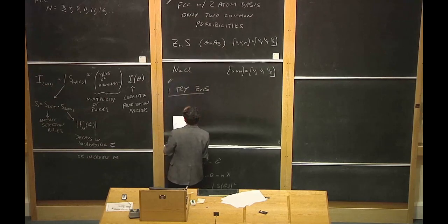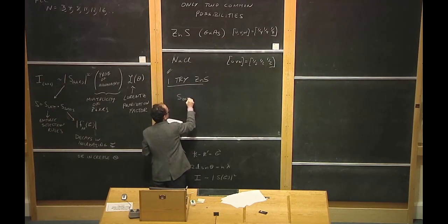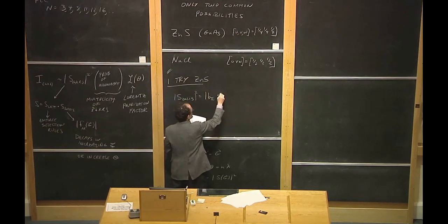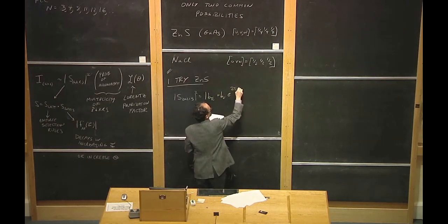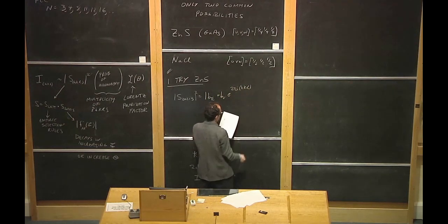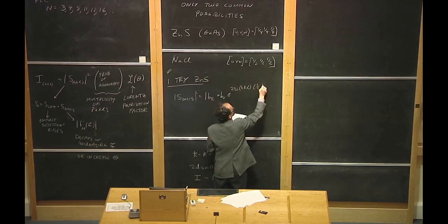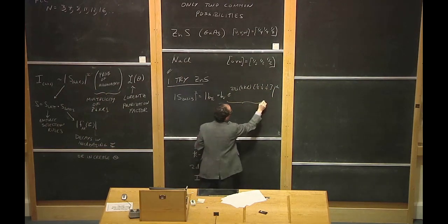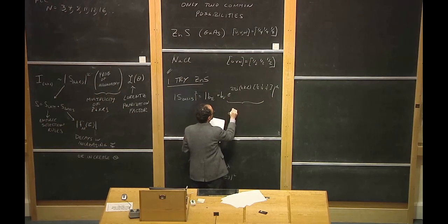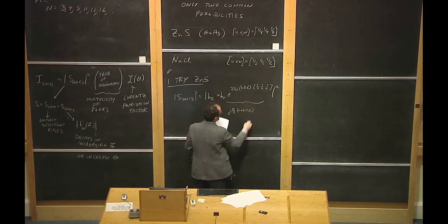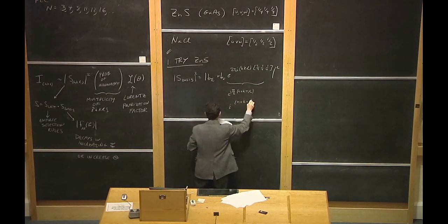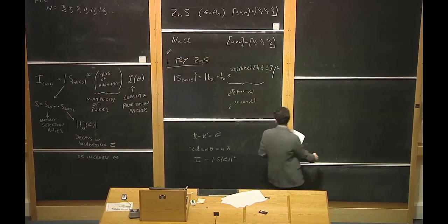Okay, so in this case, S basis squared equals, well, we have b zinc plus b sulfur e to the 2 pi i HKL, and then 1/4, 1/4, 1/4, which we can also write, this exponential factor here, is equivalent to e to the pi over 2 times i times H plus K plus L. Or equivalently, this would be i to the H plus K plus L. So, okay, I'm out of room here. Move over here.